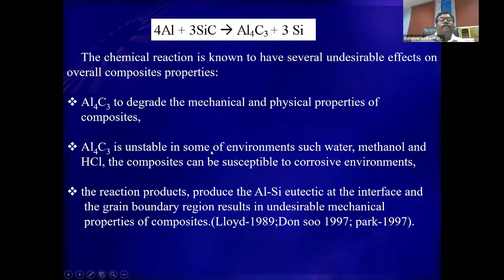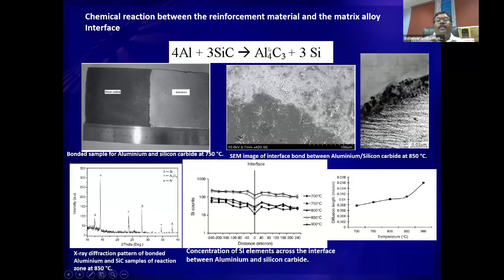So you can coat the particle, and we have also studied this. You know what effect this will have on the mechanical property, whether it is creating good bonding or worse bonding. We have taken a silicon carbide plate, and then we tried to create a bonding at different temperatures and studied the macroscopic layer here where no Al4C3 is formed. With detailed analysis with EDS and mechanical property testing, subjecting it to tensile condition, we studied the mechanical strength and the bonding, which was very, very poor. It can be easily separated with a minimum load.